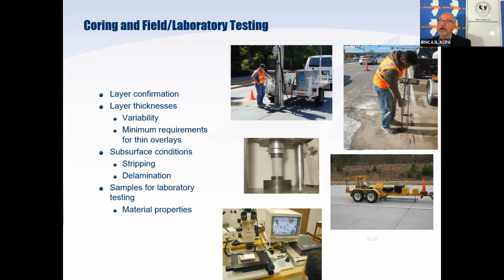We can do exotic testing. The lower right hand is a falling weight deflectometer. You can get a wealth of information from that device in a short amount of time. And if you have an important project, it's worth hiring the FWD crews to come out and actually thump the pavement. And we can use those numbers to back calculate support conditions. And basically, we calculate all of the required parameters necessary to design the overlay.